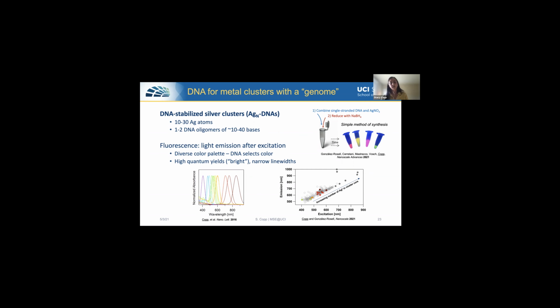And there's another favorable property of these clusters, that is that they can be very brightly fluorescent. So one measure of this is what's called the quantum yield. It's the fraction of photons that will be emitted by the cluster per number of photons that it absorbs. So these clusters can have very high quantum yields. They can also have narrow line widths, meaning that these spectra here and also the fluorescent spectra are not very broad, and that can be useful for applications.